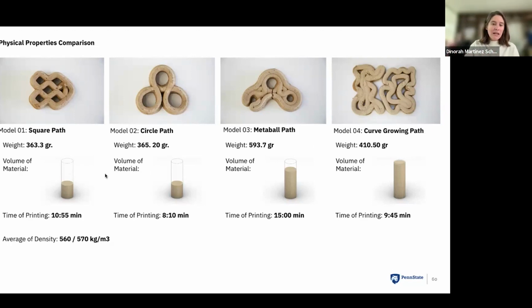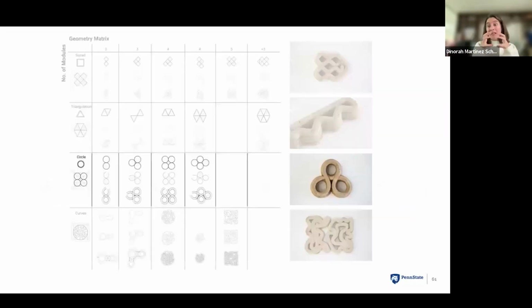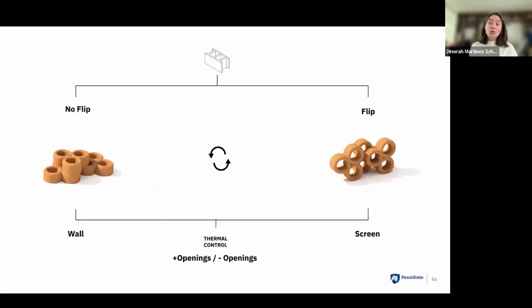So I selected the circle and the square, and as you can see, they only use 8 or 10 minutes of printing. In the end, we realized the circle was the best geometry that can work with this material. So we started to do two kinds of architectural applications. But then when I was printing, I realized two things. First of all, if I don't flip the bricks and I just stack them one on another, I can get a wall. That is the first architectural application. But if I flip the brick, I can get a screen.